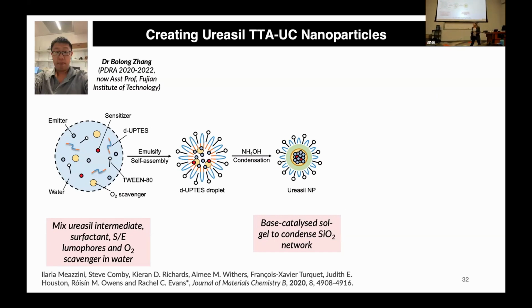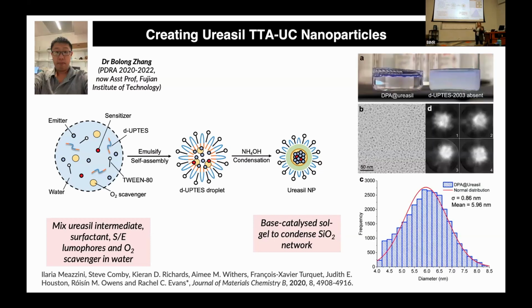And so basically you do an emulsion process. We form these droplets, and then we condense the silica structure on the surface to form a silica coating. And we're able then to get nanoparticles of around 6 to 10 nanometers in size in dispersion. We know that the d-UPTES is important because if we just have all of the other ingredients here, then actually we get this really cloudy dispersion. So you don't get the nanoparticles forming. When the d-UPTES, our ureasil, is present, then we get this clear dispersion of nanoparticles.